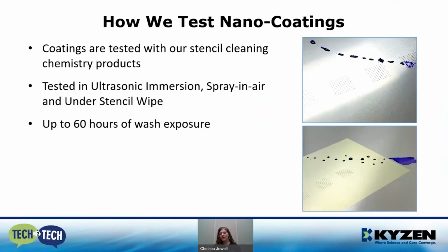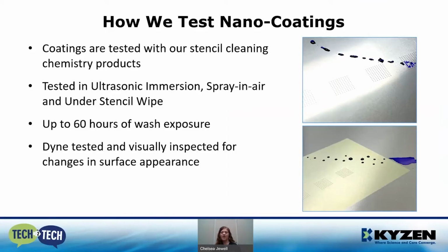Overall, we do 60 hours of wash exposure. So this stencil, once the nanocoating is applied or it comes in as a cured coating, goes into one of the machines with our chemistries, and we run typically 5-minute cycles and test after each cycle to see how the coating is holding up. This is done for a total of 60 hours of exposure.